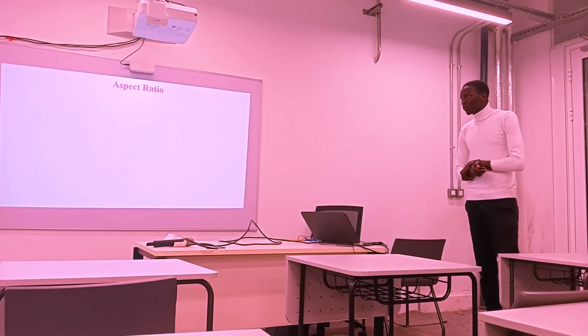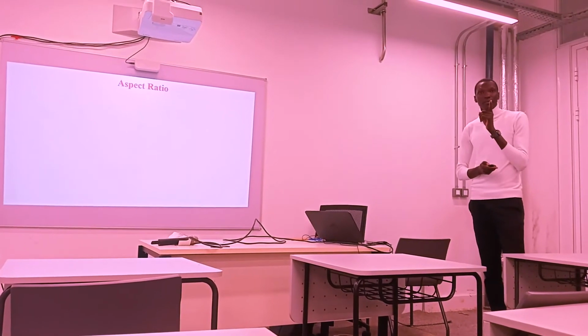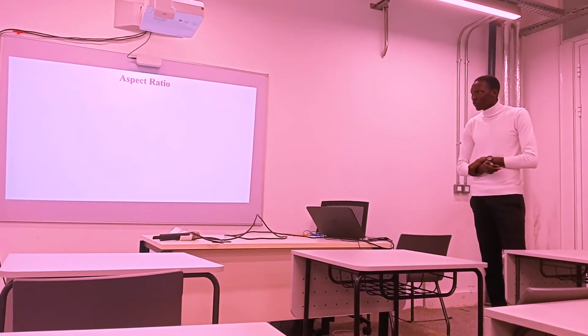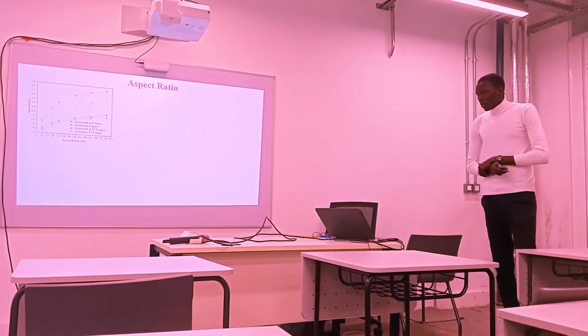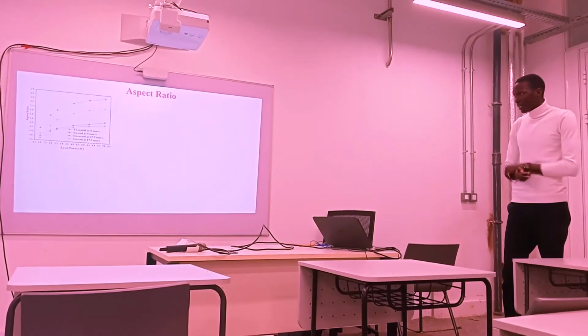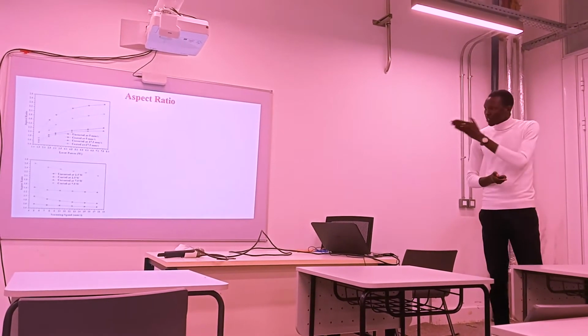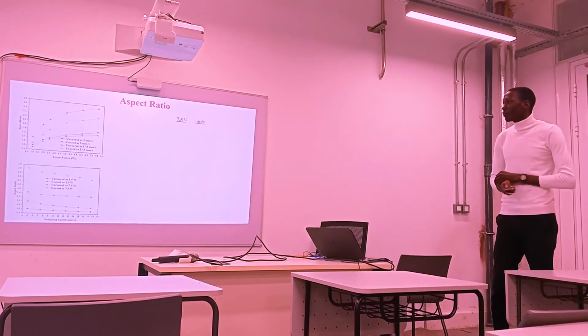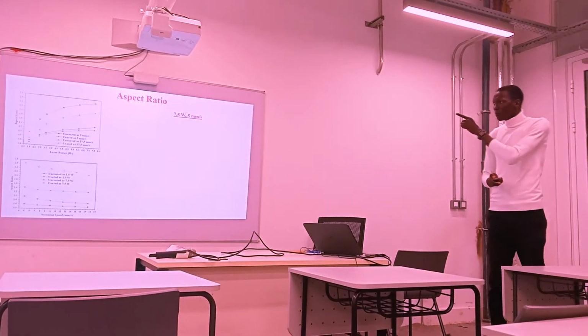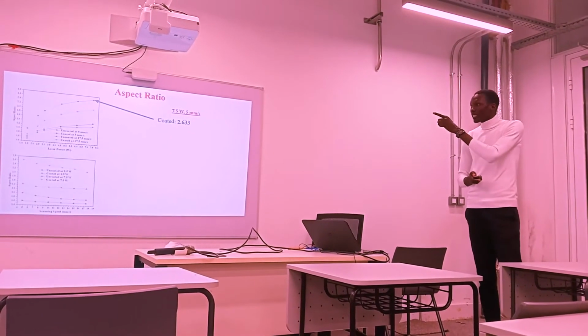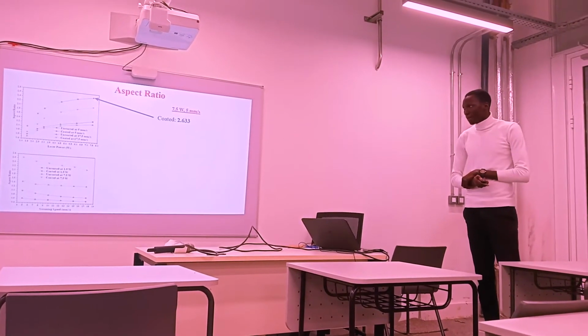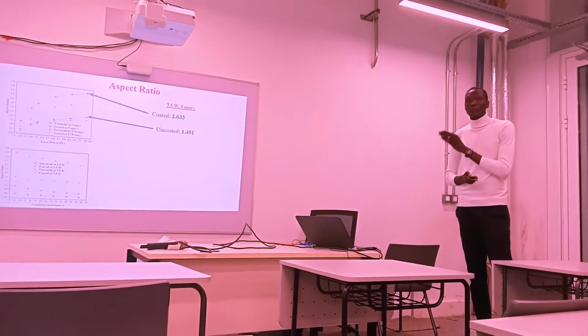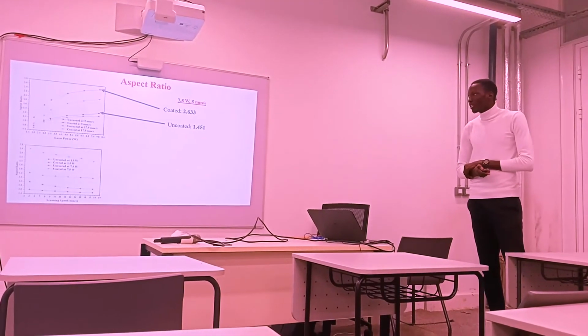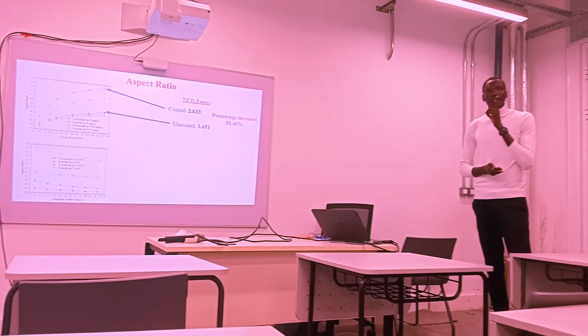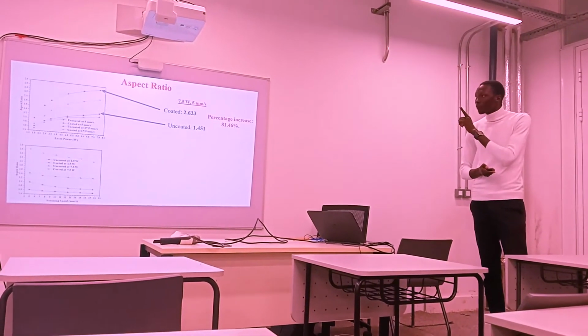Then the aspect ratio, we divided the values of the depth by the values of the width to get the aspect ratio. Aspect ratio versus power. Aspect ratio versus speed. Then at maximum power and minimum speed, for the coated, we got 2.633. And then for the uncoated, we got 1.451. A percentage increase of 81.46%.